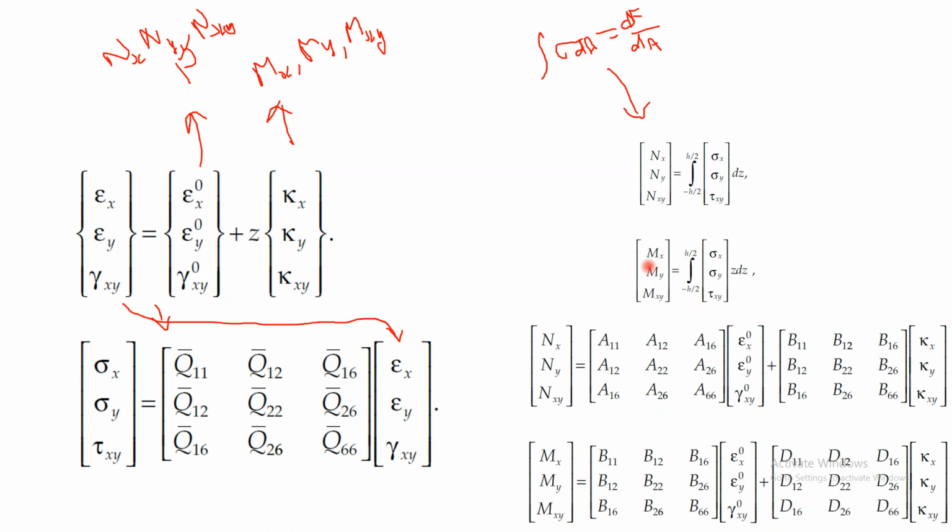That's it. So if I do these two operations, that is integrations, finally the forces are written in this matrix format, and moments are represented in this format. What you should understand from this is that Nx and Ny are the forces generated, maybe because of the normal strains and the strains due to bending moment.